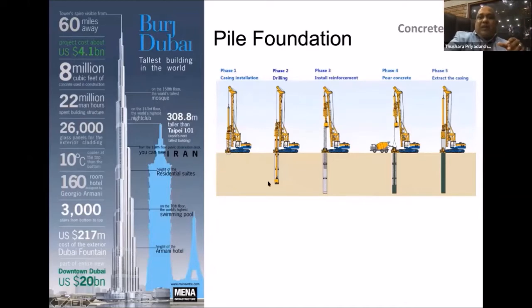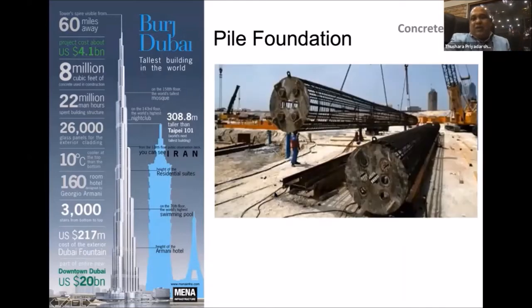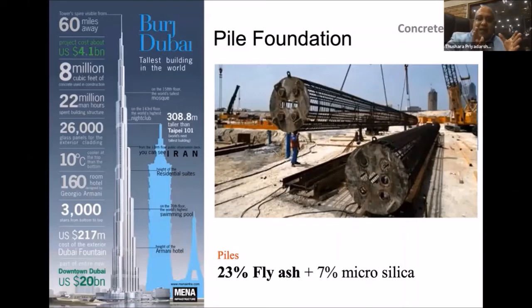So for the pile in this particular project, Burj Khalifa, they have used 23% of fly ash plus 7% of microsilica, meaning total 30% of cementitious material, except cement, replacement has been used for piles. So even you can use slag, this is up to you. But if you replace this with slag, usually it's said that you have to use double the amount of pozzolanic material or the fly ash when you use slag.